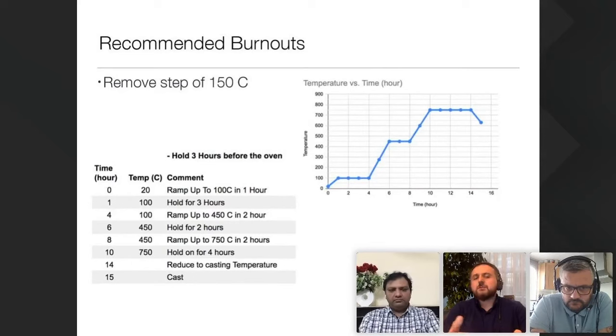What happens if you remove the step of 150 degrees? Remember what we showed before, where even though I go very much higher at 450, inside the flask it still remains at 120, 100 degrees because the water is evaporating, and then it will go up. So it can be done - I would say it is a possibility, but it's experimental.